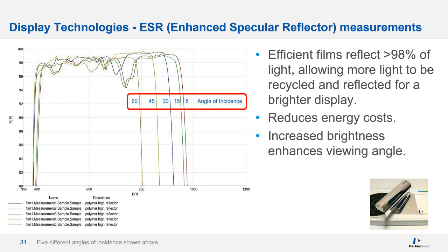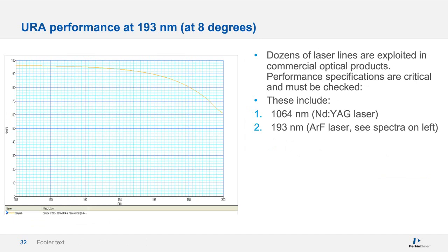Finally, we see here some reflectance data for the URA at around 193 nanometers. This is a very important wavelength for people in the semiconductor industry. Its fabrication of parts via photolithography on a substrate wafer is often performed at 193 nanometers. But it's critical that optical components are characterized at this wavelength. High reflectance values can also be difficult to measure at this wavelength, but the URA is able to perform this measurement effectively.